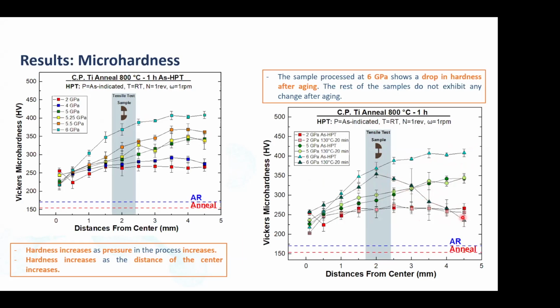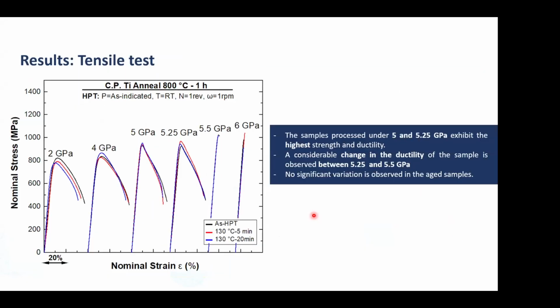So we get static recrystallization, and at this point of the aging, that's 20 minutes at 130 degrees C, we see that the material is still thermally stable, but the hardness is dropping. So probably if we increase the aging time or the aging temperature, we will see the drop of the rest of the material back to the normal or closer to the initial state. And of course, this is also related to the reverse transformation of the omega to the alpha phase.